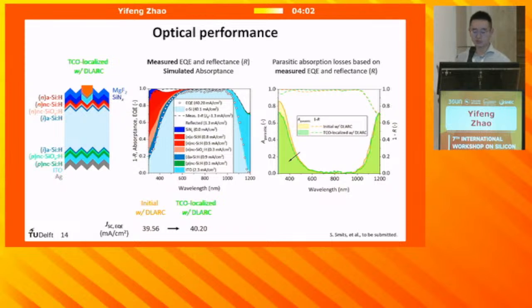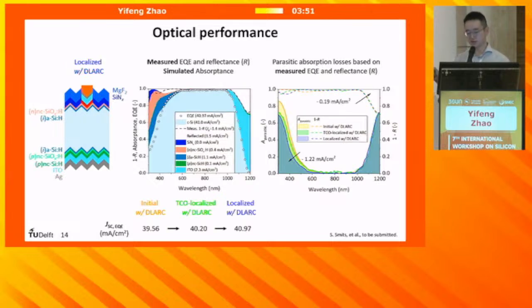Then we localized the ITO. As you can see, the JSC is improved further to 40.2 milliampere per square centimeter, and the parasitic absorption loss is reduced. Further, by localizing ITO and doped layers, we can achieve a JSC from EQE of almost 41 milliampere per square centimeter, and a parasitic absorption loss reduction of 1.22 milliampere per square centimeter. With the proven optical enhancement of this design, now let's look at the JV parameters.